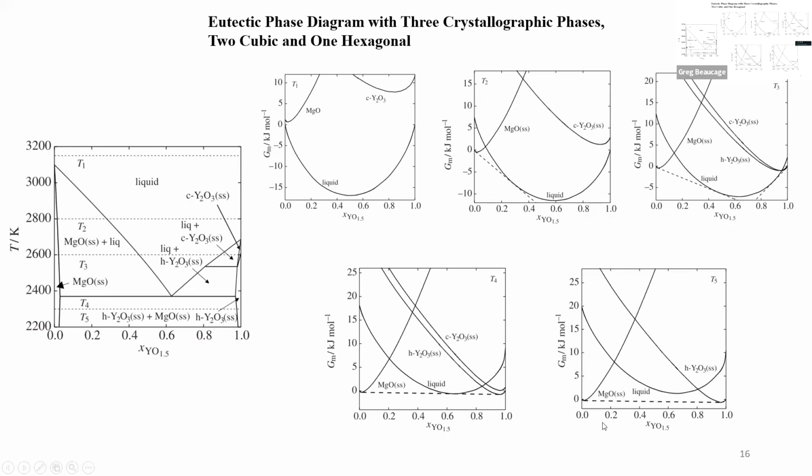Then you go below and it's just the two. So there's an equilibrium between those two and the liquid's out of the picture. Right. So just by having these three Hildebrand kind of equations, you can predict the eutectic. You fully predict it. So that means what you need are the heat of melting for the three crystals and the melting temperature of the three crystals. So 6 parameters. And that's it. If you assume ideal, you need 6 parameters to predict this whole thing.